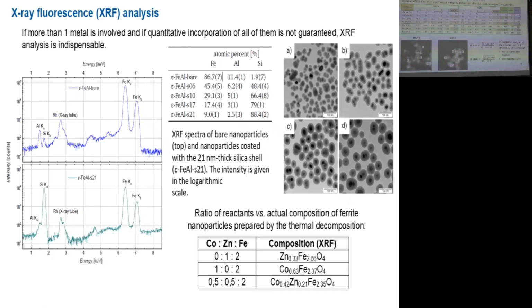And for that case, you need another analysis. As I mentioned, if you prepare a sample containing two or more metals, and if you apply some procedure where it is not guaranteed that all metals are incorporated, then you should analyze the chemical composition of the product. And you should analyze it on the macroscopic level, namely by X-ray fluorescence analysis, which is analogous to EDX in TEM, but this is a separate analysis on a macroscopic sample, which is optimized for accuracy, and it can be calibrated well. So you can get some reasonable accuracy, and it's really important analysis, and I will demonstrate it on this case.